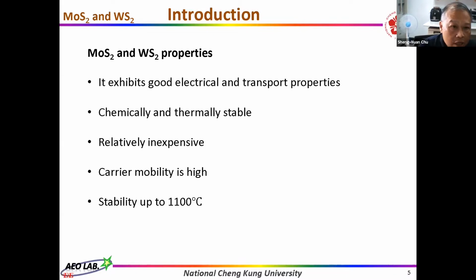In this work, I will talk about MoS2 mainly, because MoS2 can exhibit good electrical and transport properties, and it is chemically and thermally stable, and relatively inexpensive. The carrier mobility is pretty high, and the temperature stability can be up to 1100 degrees.